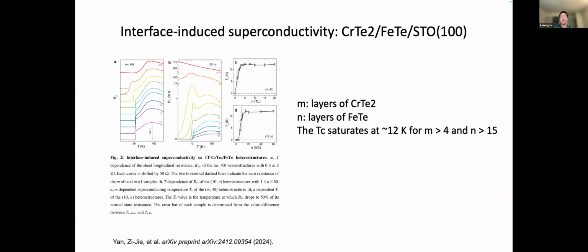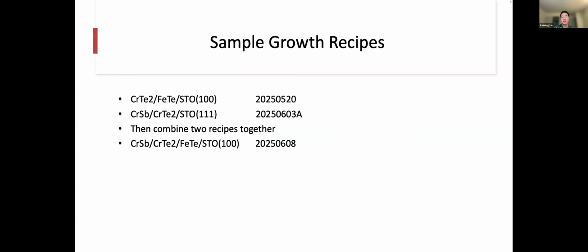So beyond quasi-particle interference, chromium antimony is also interesting for interface studies with superconductors. As shown here, the Tc for this heterostructure, chromium ditelluride and iron telluride, saturates at 12 Kelvin, when chromium ditelluride is thicker than 4 layers and iron telluride exceeds 15 layers, which is a good substrate for growing chromium antimony. And here are the 3 growth recipes we used, which I learned from Penn State.